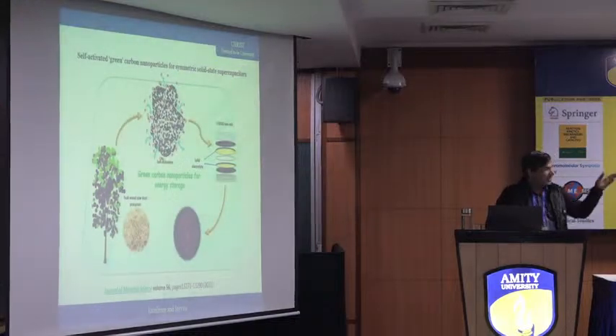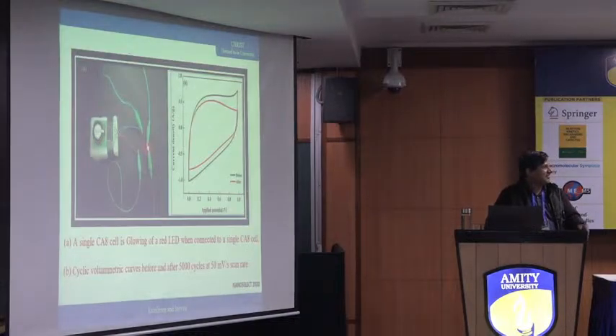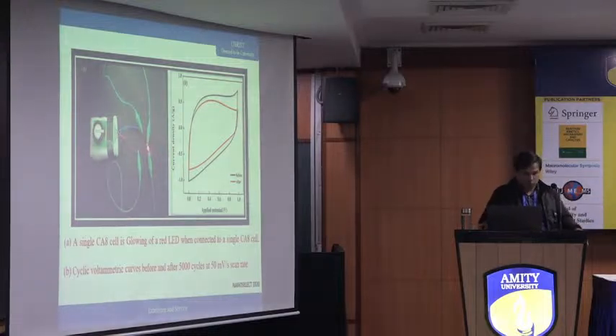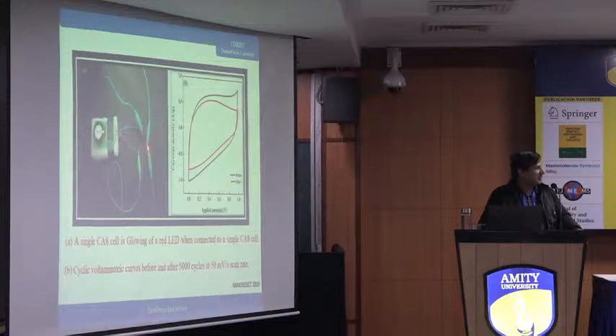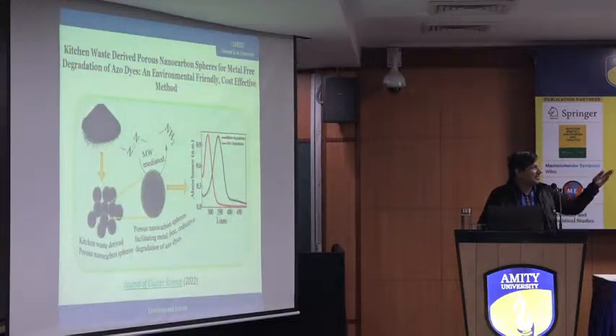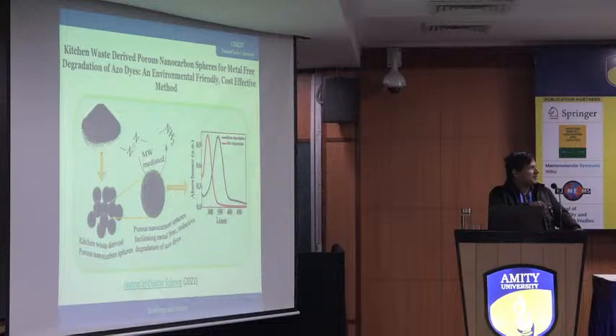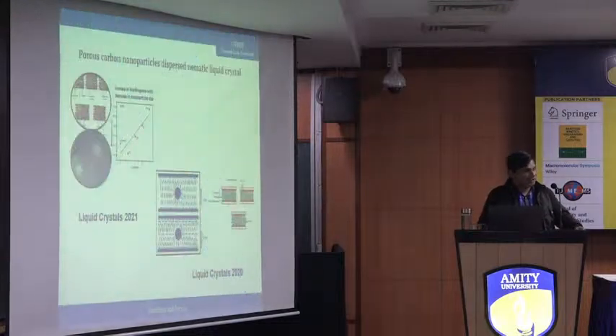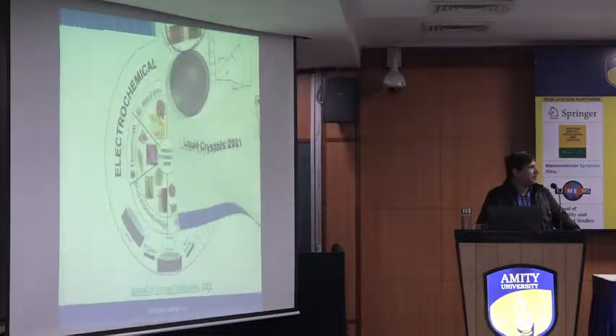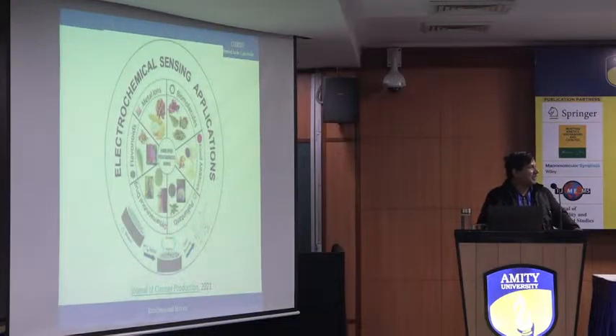These are the supercapacitors. This is one of the supercapacitors we connected with an LED, which can glow 20 minutes continuously when you charge it. And this is kitchen waste derived, a cost-effective method for catalysis application. And this is the nanoparticle with liquid crystal for displays, like in mobile phones, where birefringence drastically increases when you change the concentration of the nanoparticle. We can use nanoparticles for sensors. We are working on these things.